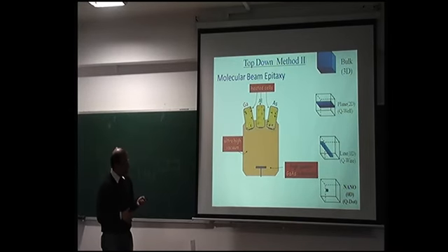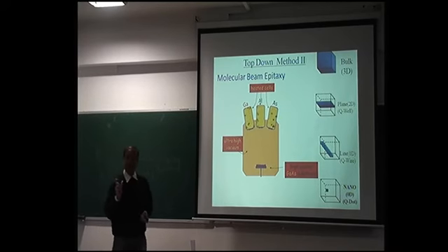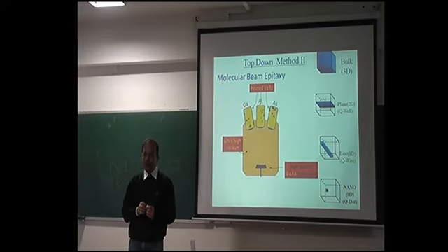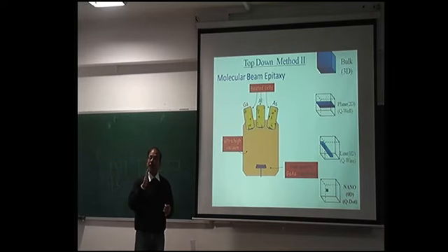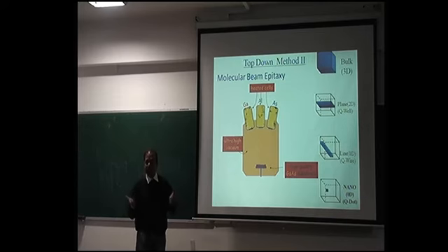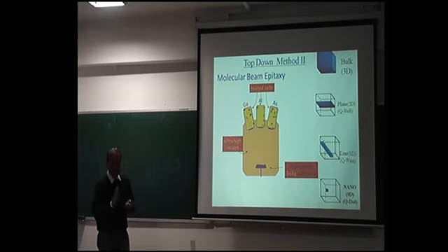Now I will open this for a certain time, and this time is not like a microsecond or millisecond. For one monolayer, you can keep it open for 10 seconds, because if it is a microsecond, it's very difficult, you don't know when you opened it and when you closed it. So you have to adjust this particular angle and vacuum in such a way that for one monolayer, you'll be allowed to keep the shutter open at least for 10 seconds.